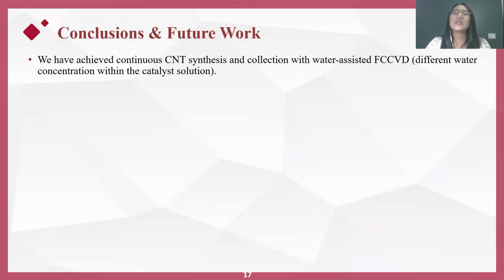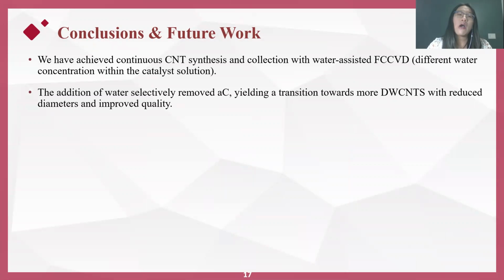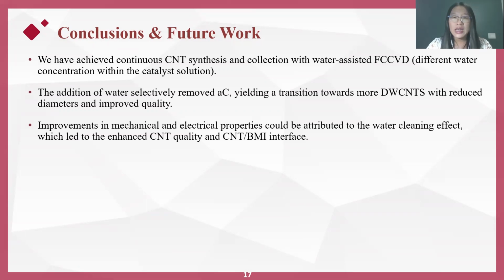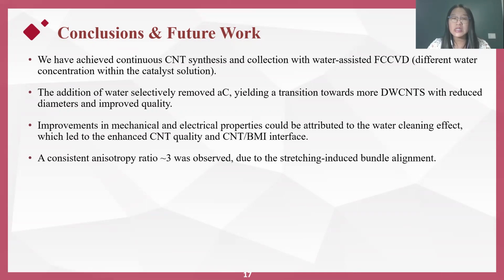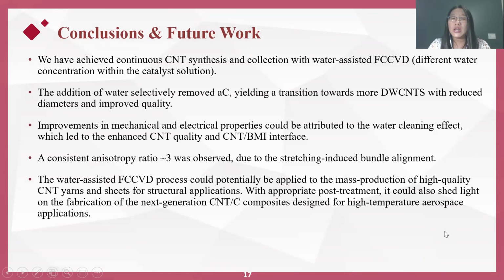So with the proposed water-assisted FCCVD process, we have achieved a continuous CNT synthesis and collection. And our hypothesis was that the addition of water selectively removed the amorphous carbon without damaging the CNT network, which yielded a transition toward more double-wall CNTs with reduced diameters and improved qualities. The mechanical and electrical properties could be attributed to the water cleaning effect, which led to the enhanced CNT quality and improved the CNT-BMI interface. We observed a consistent anisotropic ratio around 3 for CNT BMI composites due to the stretching-induced bundle alignment.